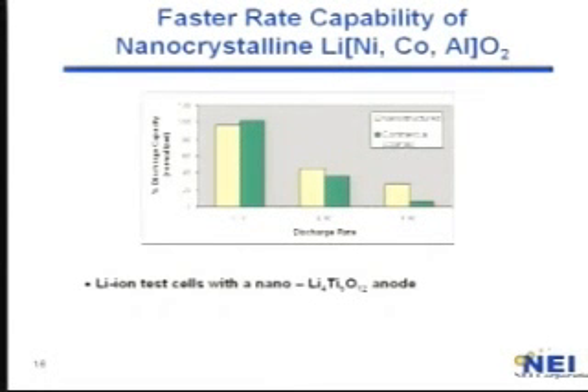And as you can see, at C/5, yes, at C/5, the capacity or the discharge rate capability of both materials is almost similar. But as you go to almost a 6-minute discharge, the coarse material, the commercial material, starts losing most of its capacity, while the nano still maintains its 30% capacity. So the nano domains are also important in terms of improving the material's discharge rate capability.